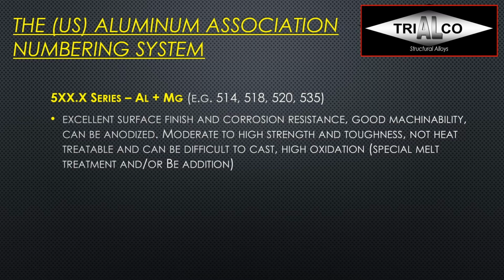be the go-to family in our foundry alloys, and you will get moderate to high strength and toughness, but pretty good ductility, even without any heat treatment, but it's pretty difficult to cast. You will get high oxidation because of the high magnesium, so prepare yourself for a special melt treatment and/or beryllium addition, which some people don't really like.